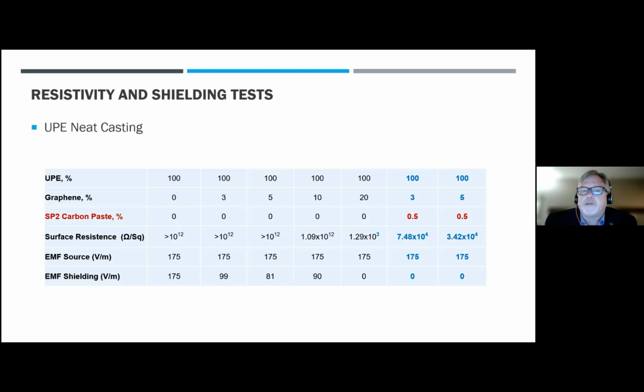We have a formula that's going to be specifically formulated for the different resin systems out there. But you'll see where at that 3% level, much lower than 20, where originally we were seeing a high amount of surface resistance that couldn't even be measured on our equipment, it is now showing improved conductivity and lower surface resistance of 7.48 times 10 to the 4th. And you can see absolute shielding in this application at that 3% graphene level with our additive. Now you go up to 5% graphene, again with the same amount of our paste in there, you start to see even a little bit better